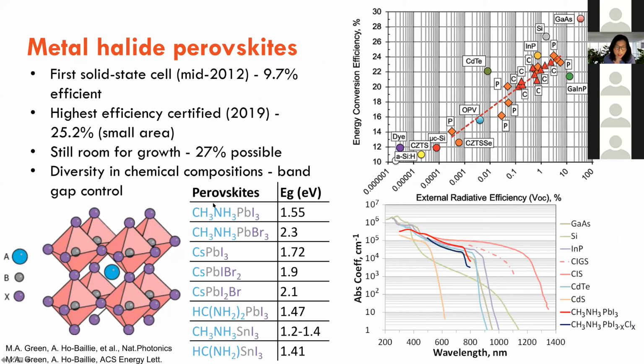And there's a diversity in the chemical composition. If you vary the organic ion into different types of organic cations, or you replace the lead with tin, or you mix it, 50% tin and 50% lead, or you mix the iodide and the bromide, 50% or 15% usually, then you can tune the band gap. So it makes it a very versatile material, and that means you can use it for tandem. The optical absorption coefficient is very good. It has low non-radiative recombination. It has high potential for high efficiency.